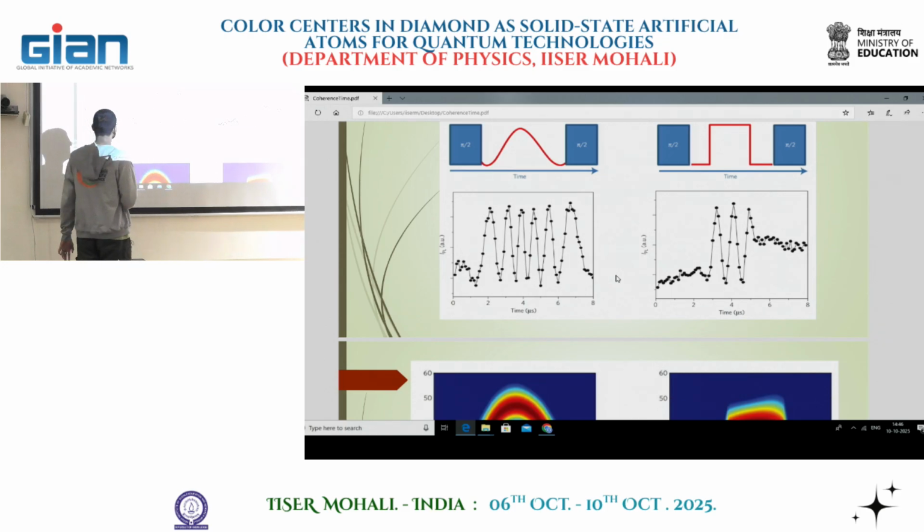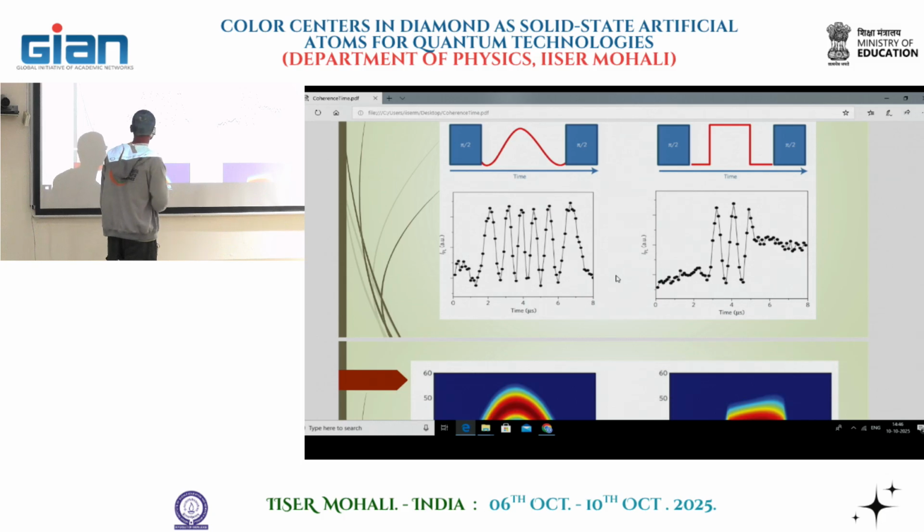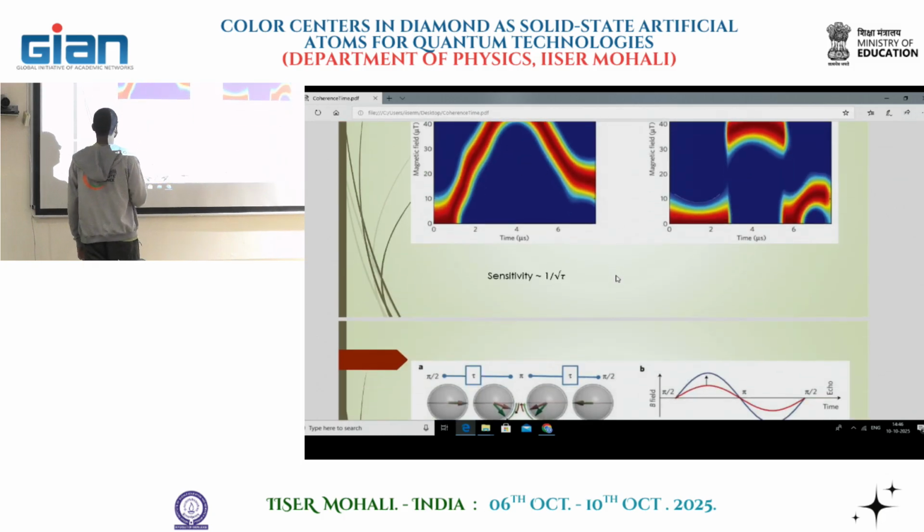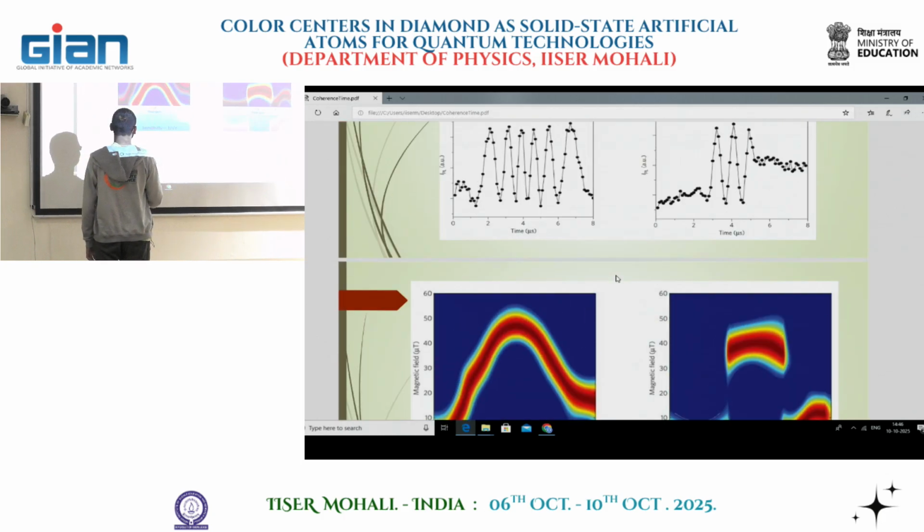Over here, you can see that you get this oscillation kind of thing. That is the intensity profile with the evolution time tau, and you can map this. There was a formula in the paper, relating phi and the magnetic field B. So you get these kinds of oscillations, and if you do a wavelet transform, you basically reproduce the pulses